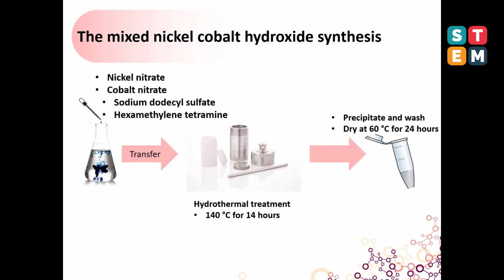For the methodology, the mixed nickel-cobalt hydroxides were synthesized by facile hydrothermal treatment at 140 degrees Celsius for 14 hours. The nickel nitrate and cobalt nitrate were reduced by hexamethylenetetramine, and sodium dodecyl sulfate was used to control the morphology of the crystal.